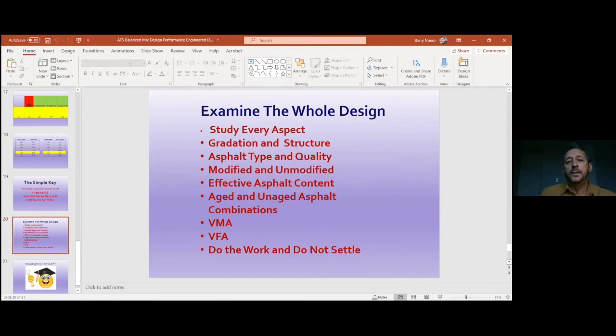So what I'm saying is study every aspect, the gradation structure, the asphalt type and quality. I have seen passing SCBs on anything from a PG67 to our PG70 SBS, PG70 latex, SBS PG76, and crumb rubber modified. And we no longer make the 82 that Sam referred to. We now have to meet a 76 with crumb rubber, but we still have to meet the MSCR. And we found ways to meet that as well. And they're all working good in this state now.